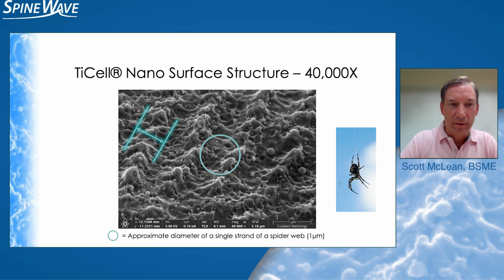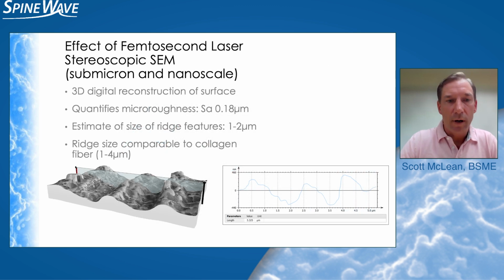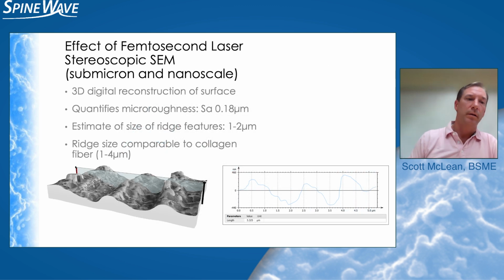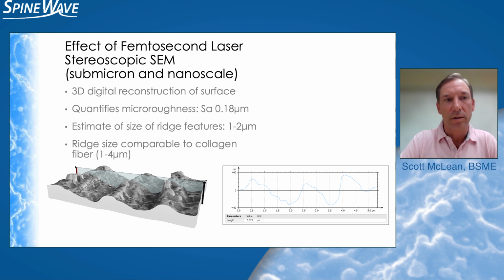If you look even a little bit closer, you can see the melting and recasting material along and between those pits has left very small features that are at the nanoscale. In order for us to quantify the features at this scale, we use a tool called stereoscopic SEM. We produce a digital reconstruction of the surface.